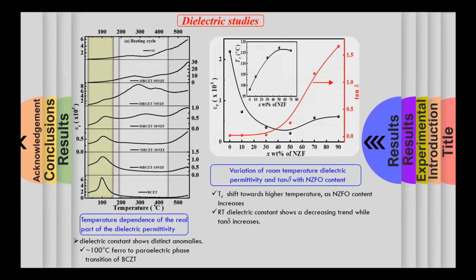In this case, it is 50 weight fraction of piezoelectric and 50 weight fraction of nickel zinc ferrite. So if we compare it with this, the weight fraction of piezoelectric phase is much less. So obviously the response will decrease. Because the weight fraction is decreasing, you have less volume fraction of the piezoelectric phase. So obviously its effect will keep on decreasing.